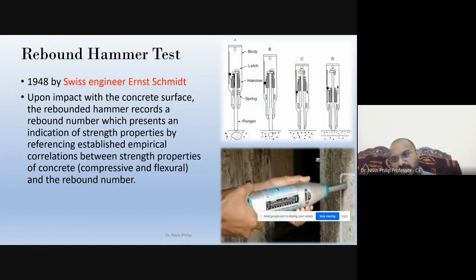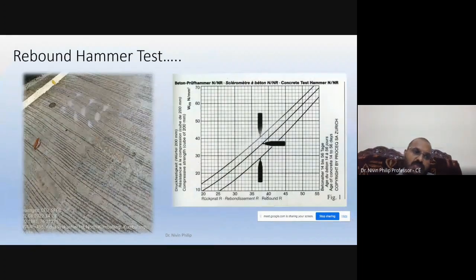So the rebound hammer, most of them know. We are measuring the rebound number from the concrete surface. I didn't go for the theory. One thing you should know: when you're going for a rebound test, if one point is concerned, we should take the average of 9 points. The surface should be smoothened, then only go for the rebound hammer test. Based on the position, how we are holding the hammer, we will get the result based on this curve. So when you are checking one point, you have to take at least 9 points, like a grid you have to form. Otherwise, the accuracy is only 15 to 20% variation will be there with the composition of the cube. So we normally will take the average value.